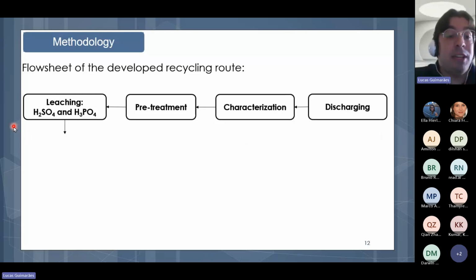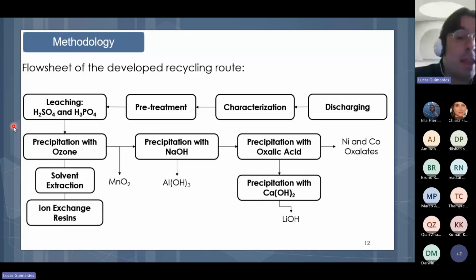After that we have leaching with sulfuric acid and phosphoric acid, and then purification techniques were tested, such as precipitation with ozone, solvent extraction, and ion exchange resins. But precipitation with ozone was the one chosen to follow for the next steps. In this precipitation, we could remove manganese oxide. The next precipitation was with sodium hydroxide, in which we could recover aluminum hydroxide. Then precipitation with oxalic acid, in which we could recover nickel and cobalt oxalates. And at the end, precipitation with calcium hydroxide, in which we could recover crystallized lithium hydroxide.